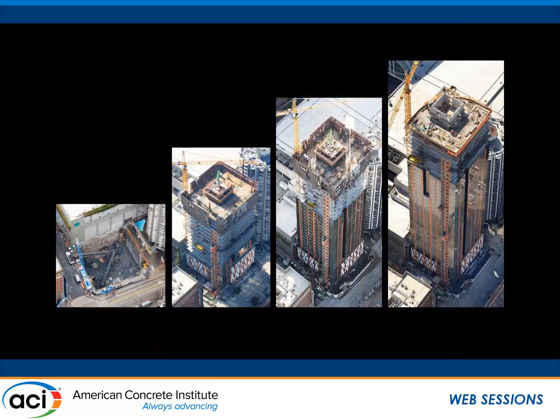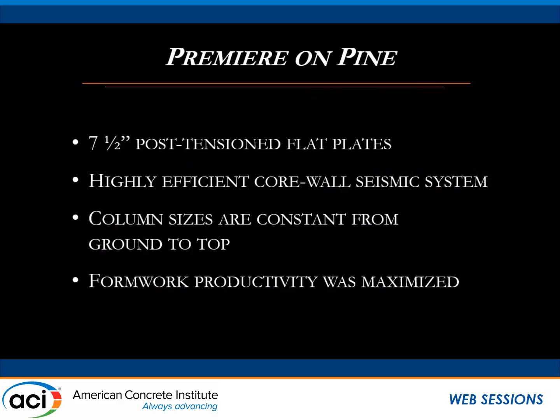Here's the building growing up. You can see it coming out of the hole on the left and then growing up on the right. The 15,000 PSI concrete, which we did use in all of the columns, and Joe will talk in a lot more detail about that, but we did use 15,000 PSI column concrete. We started that down at the base, and that migrated upward to 8,000 PSI up at the top. Some data on the building, 7.5-inch PT flat plates throughout, highly efficient core wall seismic system.